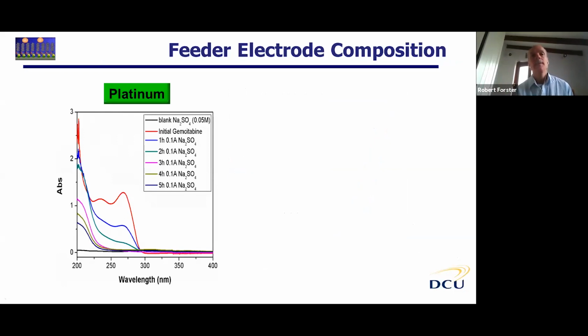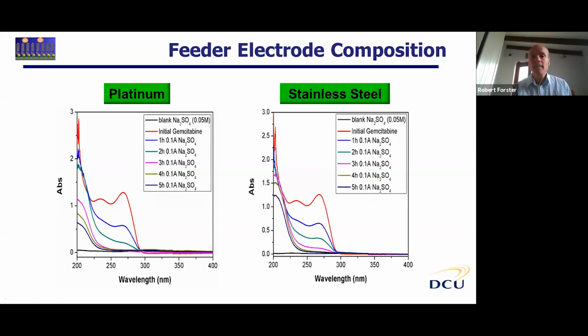So conventional spectroscopy, UV-Vis spectroscopy, is a good technique. What you're looking at here is the initial UV-Vis, then electrolyzing for an hour, two hours, three hours, four hours. After about three hours, you can see a complete collapse in the band at about 275 nanometers. We can then sample that reaction solution, do HPLC, and confirm there are no degraded organic products left - it has in fact been mineralized, which is a very exciting development.